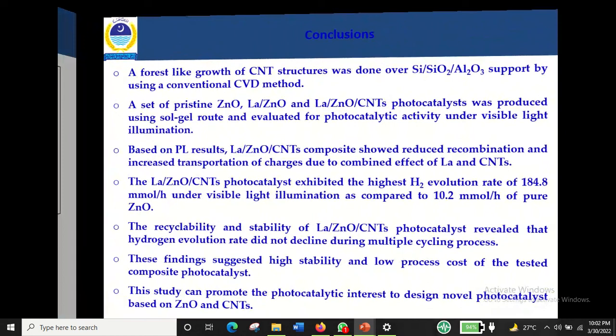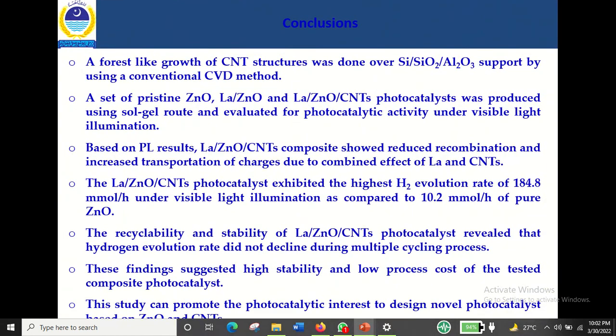So, conclusively, a forest-like growth of carbon nanotubes was conducted over SiO2-Al2O3 support by using a conventional horizontal CVD method, where ferrocene was used as a catalyst and ethylene was used as a precursor gas. A set of pristine ZnO, lanthanum ZnO, and lanthanum ZnO carbon nanotube photocatalysts was produced using the sol-gel route and evaluated for photocatalytic activity under visible light illumination.